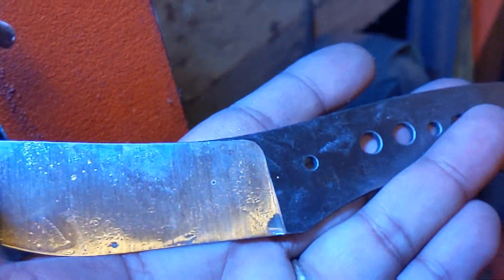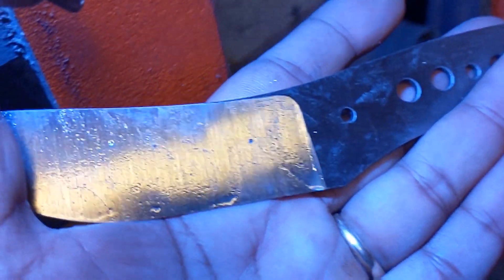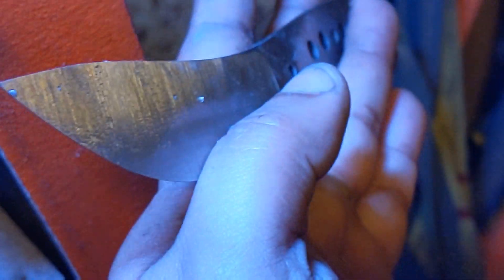We're going to send this out and make it into a razor — not making knives to chop nails at this moment. The key takeaways from this testing are that edge stability and raw toughness are completely different things. They get lumped together, but they're different. With edge stability we want thin geometries and microstructures that support that, but that's probably not conducive to raw shock toughness, where you want the microstructure to have more give and the strength to keep it from rolling with thicker geometry.